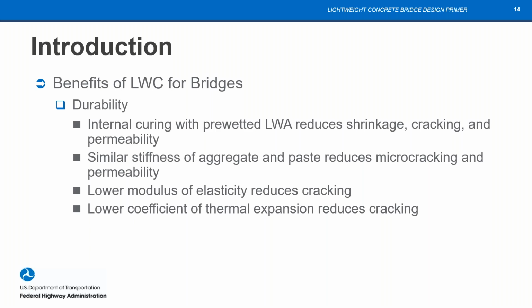But then there's something that's sort of a surprise to many engineers, and that is that durability of lightweight concrete is actually enhanced over normal weight concrete. Everything else being pretty much the same. It doesn't seem to make sense that if you're taking a rock with holes in it and you're putting it into your concrete, that it's going to be more durable than when you use a hard rock piece of aggregate in your concrete. There are a number of factors that enter in there. I can't develop that all. That's a very interesting topic, but one of the things is that the lightweight aggregate is typically pre-wetted before we put it into the concrete, and that helps with pumping it and other things.